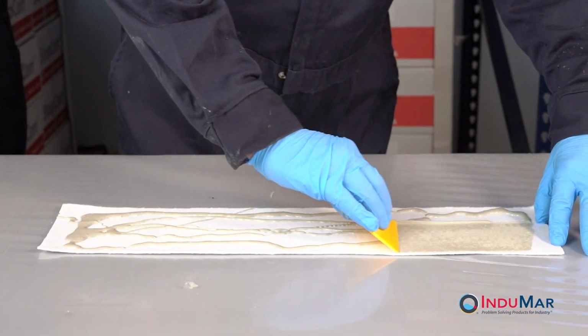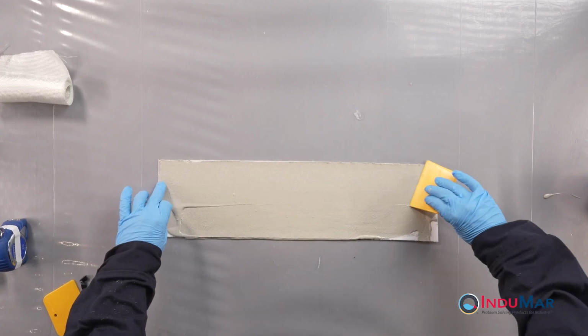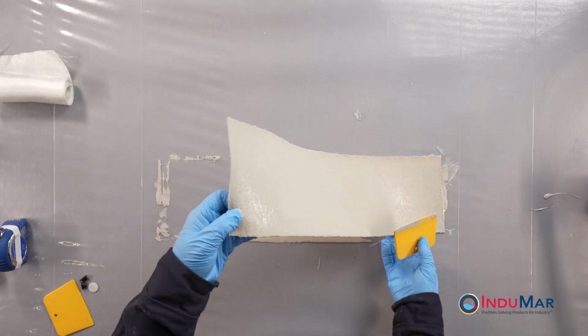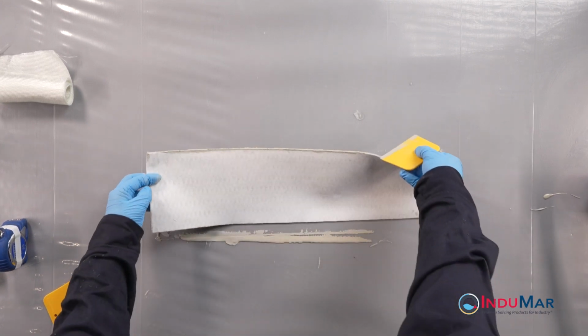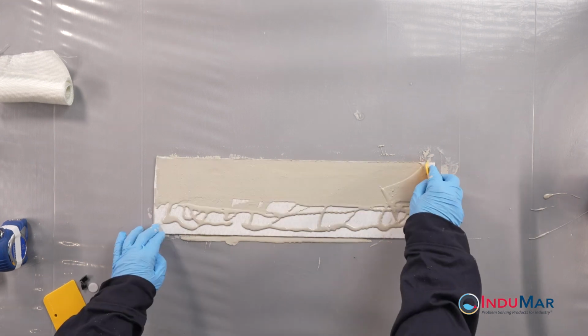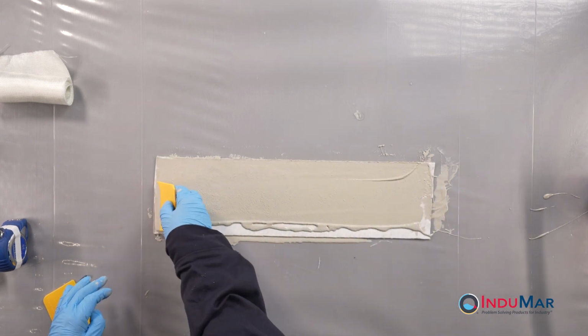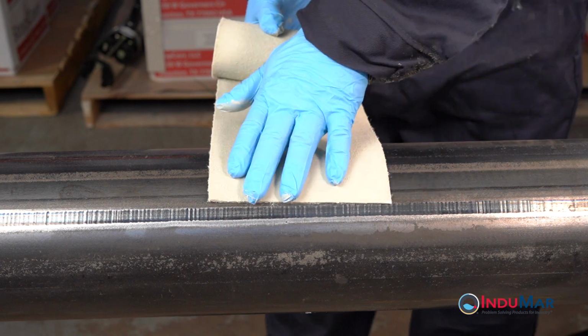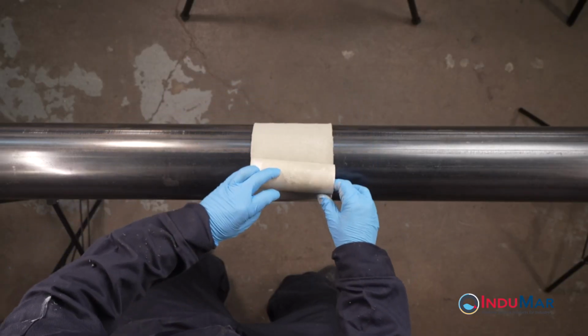Wet out enough felt to complete a single layer wrap around the entire circumference with an approximate 1/2 inch overlap. Using the provided spreader, work the resin into the felt with long strokes and downward pressure. Apply the felt to the pipe, locating the seam of the felt wrap away from the leak site.